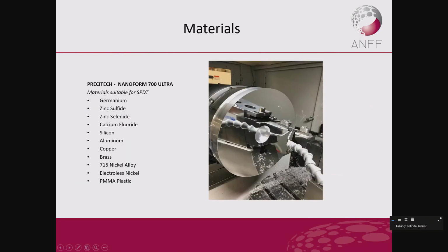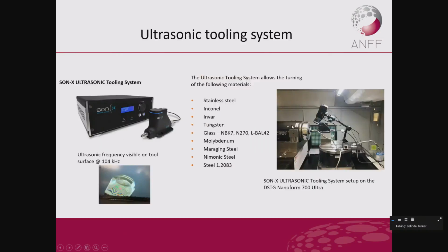And this is the sort of surface finishes you're getting. Some of the materials you can machine. Obviously, it can't traditionally machine carbon steels because the carbon on carbon will actually form a chemical reaction and wear the diamond very quickly. To get around this, DSTG have actually brought in this ultrasonic. So this is reciprocating the tool at 104 kHz, which reduces the tool wear and allows you to machine some of the steels and other materials you can see here without wearing the tool.